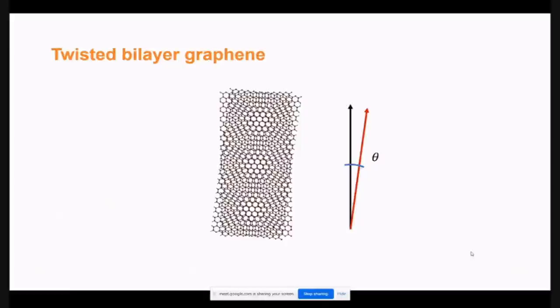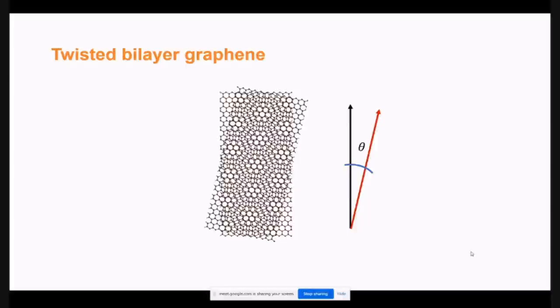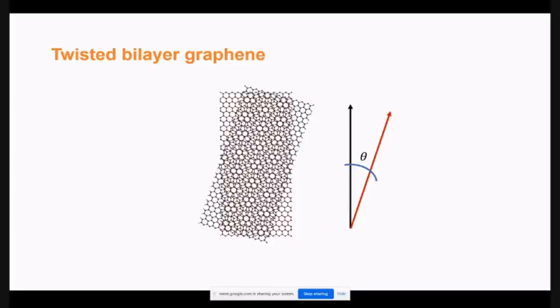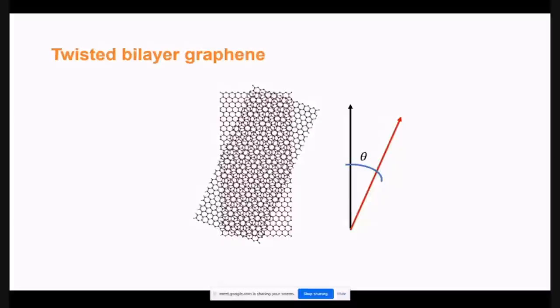Now we can twist it. We can just rotate one with respect to the other, and this is something which students here can do very accurately, and this has led to a very interesting set of activities. I'm going to talk just about one. You can change this angle at your own will, and as you change the angle, you create these larger scale structures called a moire lattice, whose lattice parameter is much larger than the unit cell of the individual graphene layers. So it's like a new superlattice that you can form by stacking two layers of graphene, and you can change its lattice constant by changing the angle between the two layers.